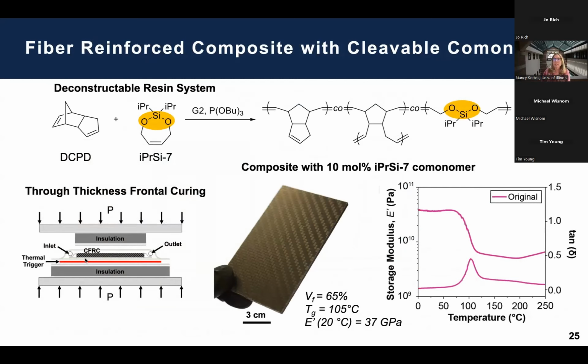The idea is that we can take this same resin system that we looked at quite extensively, its deconstruction, and put it into a carbon fiber reinforced composite, similar to using the techniques I showed you before, using a very rapid through thickness cure. So we make this thing in less than 2 minutes. In this case, we started out with a lot of comonomer. This is the 10 mol%. This is to make sure it deconstructs.